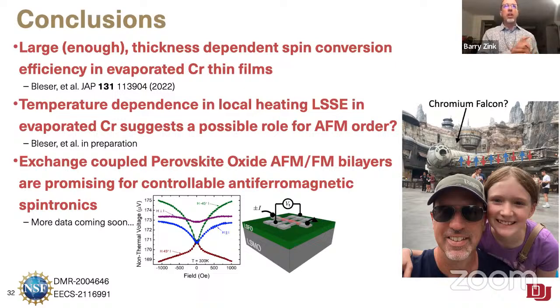What I've told you about today: we have these large thickness-dependent spin conversion efficiency in evaporated chromium thin films. That was the beginning of what I think is the story of the antiferromagnetism actually playing a role in spin conversion in chromium thin films. I showed you more evidence of that with the temperature dependence of local heating spin-Seebeck experiments. And I think that's a fairly clear, maybe not utterly conclusive, but fairly clear picture that the antiferromagnetism should really be thought of more seriously in chromium for these types of physics.